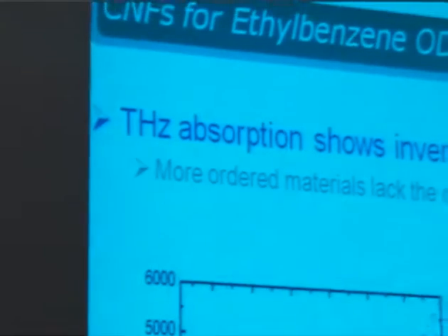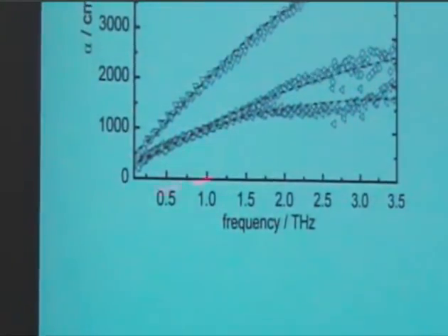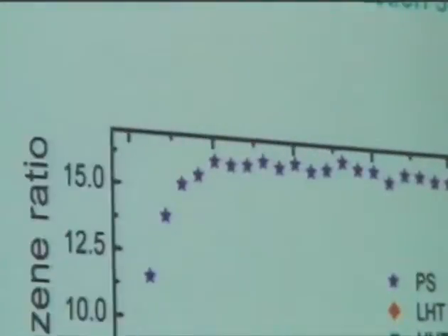Now, if we look at the terahertz spectra of these materials, what we see agrees very well with this. So, for instance, if we take the material prepared at the highest temperature, which we're expecting to be the most graphitic in nature, we see this has quite clearly the highest absorption. Conversely, the material prepared at the lowest temperature has the lowest absorption, because that's the least graphitic material.